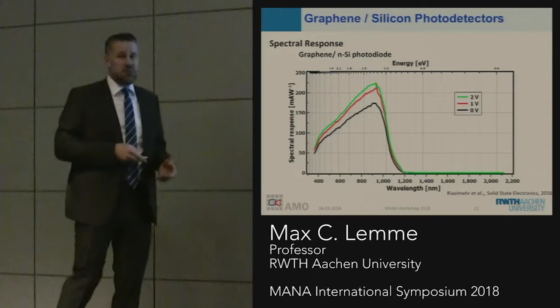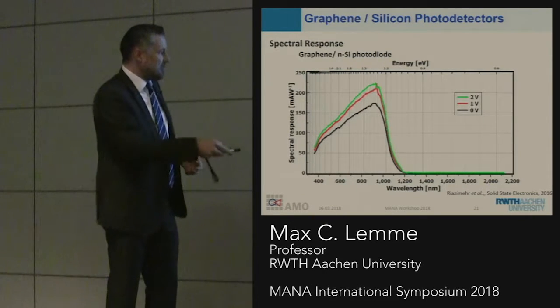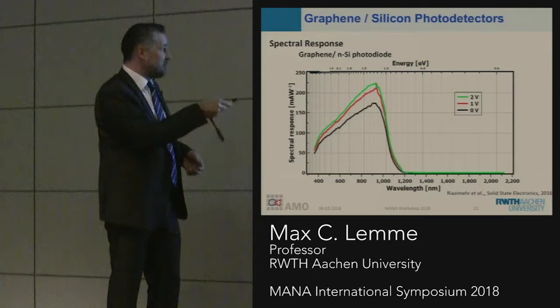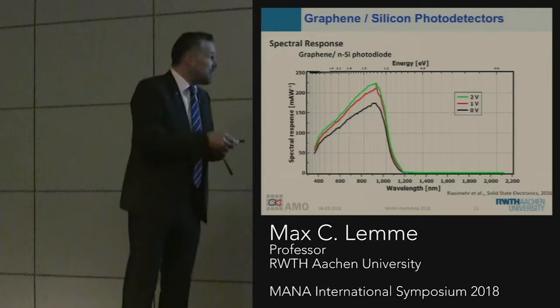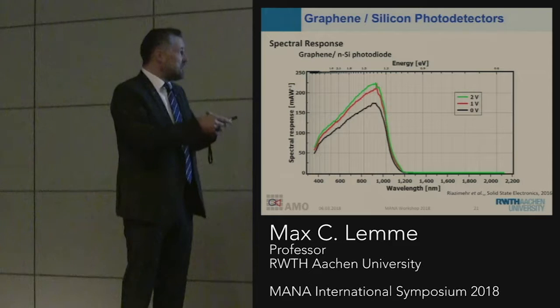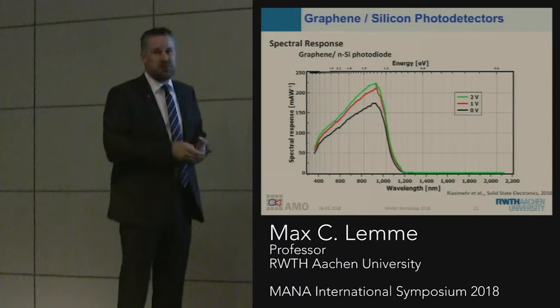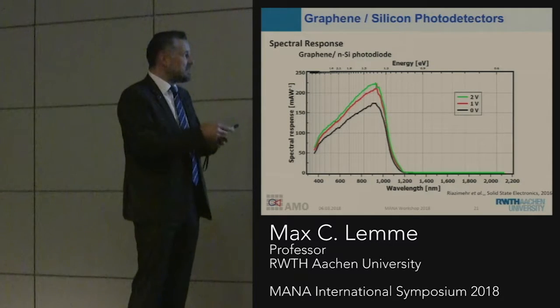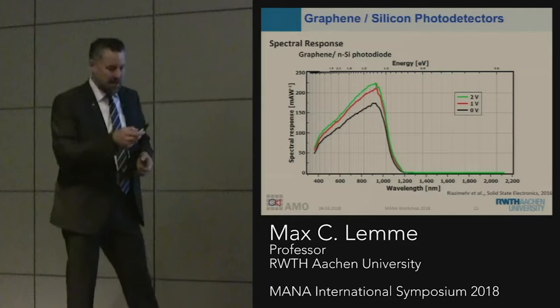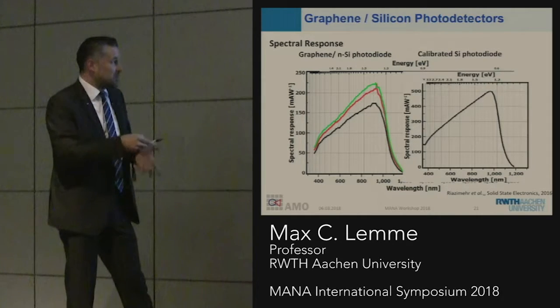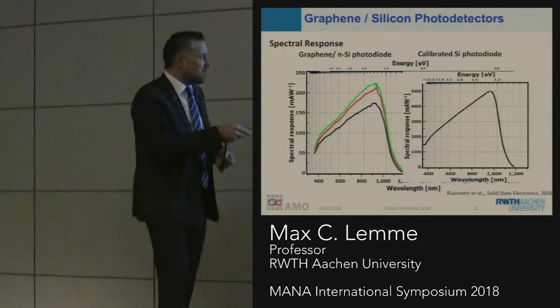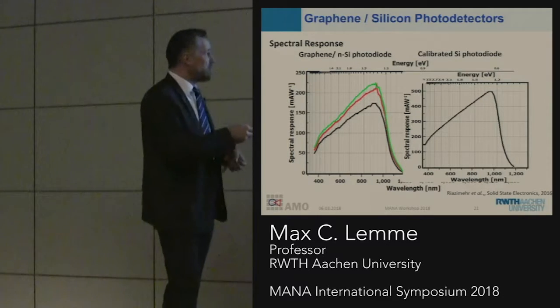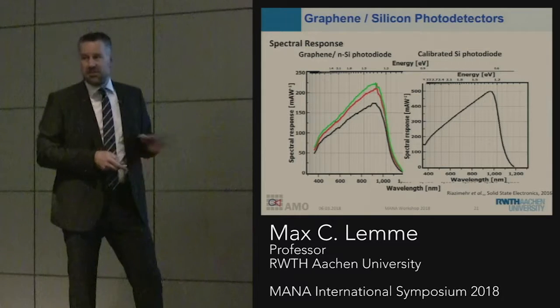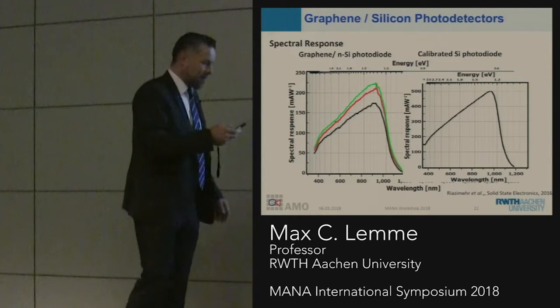So this is the spectral response of this diode - this is the wavelength, and this is the spectral response in milliamps per watt. You can see this strong response here, which happens to be the response of the silicon, so we're really detecting here in the silicon. We compare that to a commercial Hamamatsu diode - the shape looks pretty much the same. Hamamatsu diodes get about 500 milliamps per watt; with this one, we get about 250, so about 50% of the commercial diode.